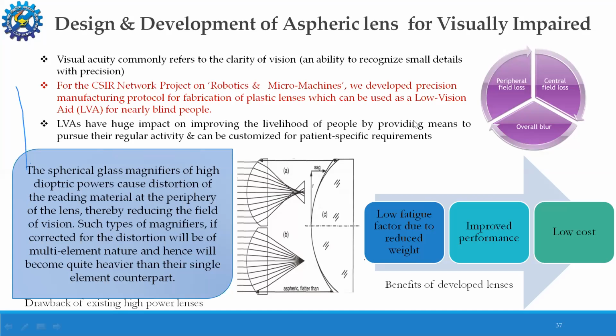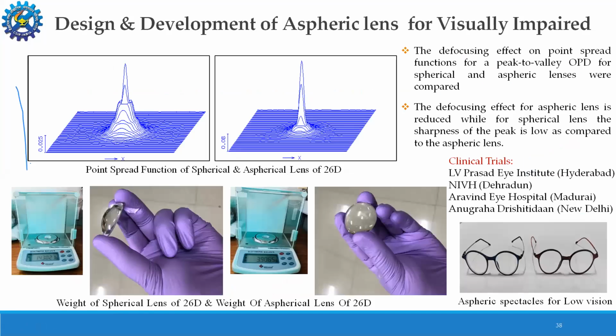we replaced the spherical with aspheric lenses and glass with plastic lenses. So it led to a low fatigue factor due to reduced weight, improved performance because of less distortion, and low cost because of replacing the glass with plastic. We compared the performance by studying the defocusing effect on the point spread function, peak to valley, for spherical glass as well as aspheric lenses. It was found that the defocusing effect for the aspheric lenses was comparatively reduced, and we get a sharper peak showing less distortion as compared to the spherical lenses.